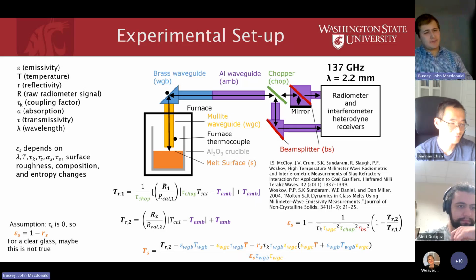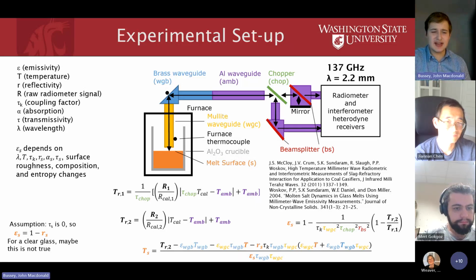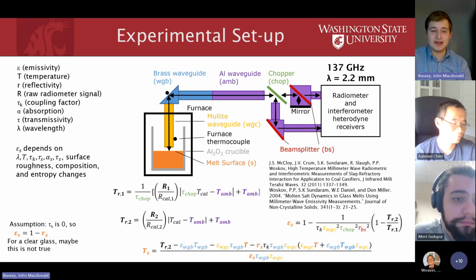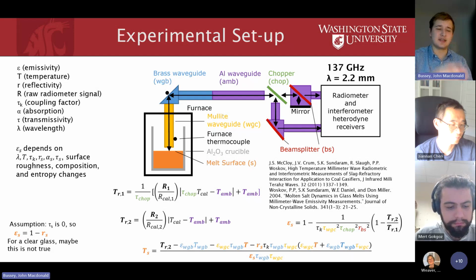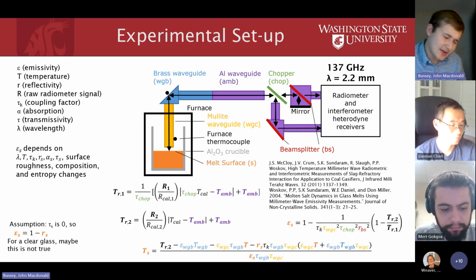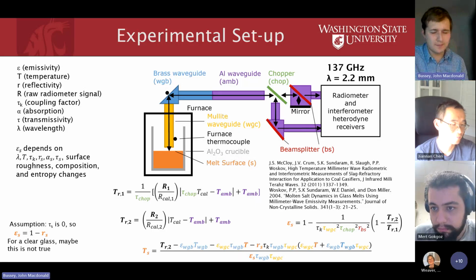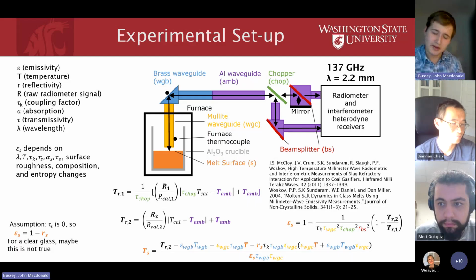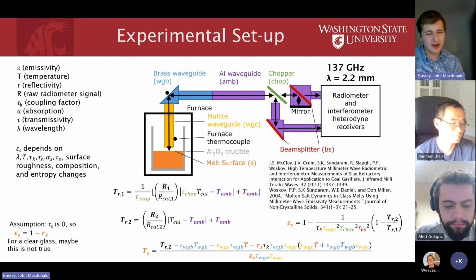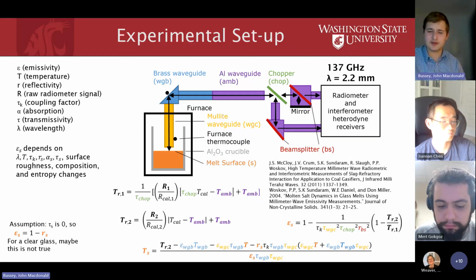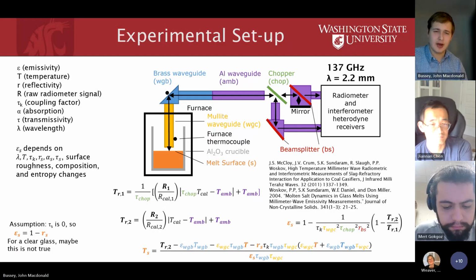So the assumption that we have to make to be able to do this is that transmissivity is 0. So all of the thermal radiation is reflected off the surface or emitted by the surface. None of it is transmitted through the sample. And so this was probably true for the black glasses this was initially looked at for the Savannah River project, where, as I mentioned above, Woskov and coworkers worked on it. But for clear glass, maybe this isn't true. And so this is one challenge with this method that I'll talk about here in a minute.